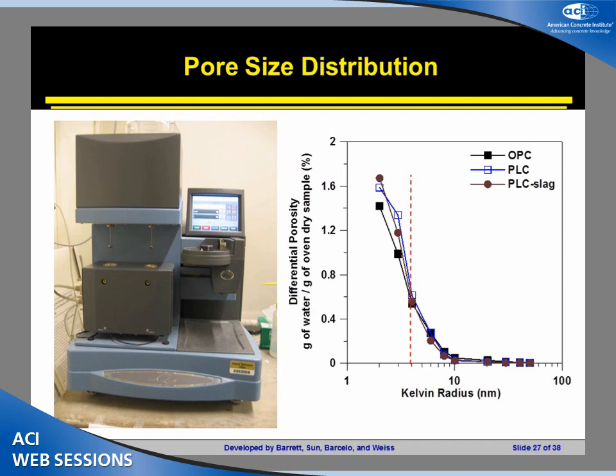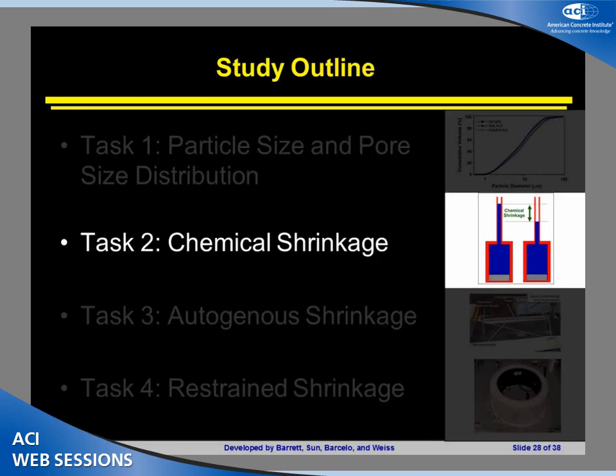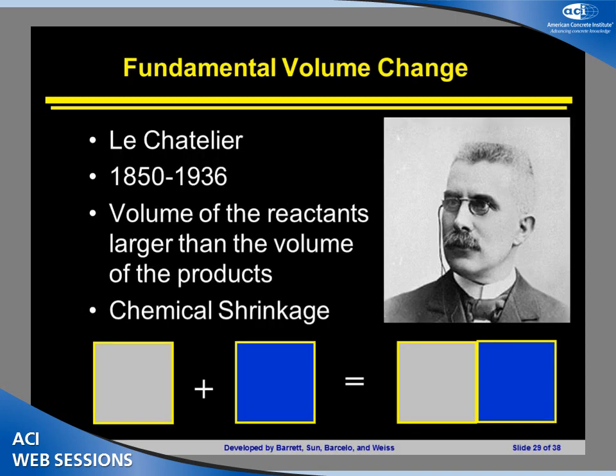We see a slight increase or a slight difference here with the PLC and the PLC slag systems, and those would be at about 55% relative humidity, where you might see a slight increase in the volume of the pores. But in general, these pore size distributions are very, very similar, even though the Blaine fineness numbers are very different in those cases.